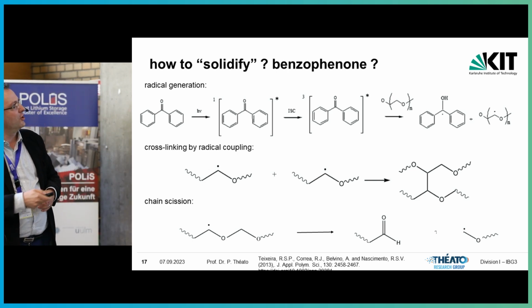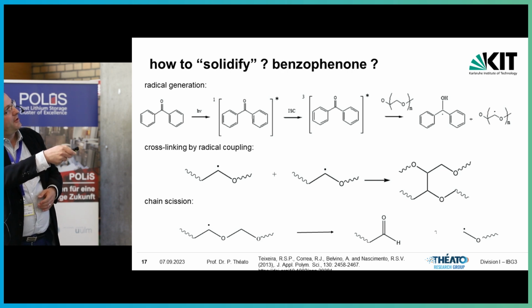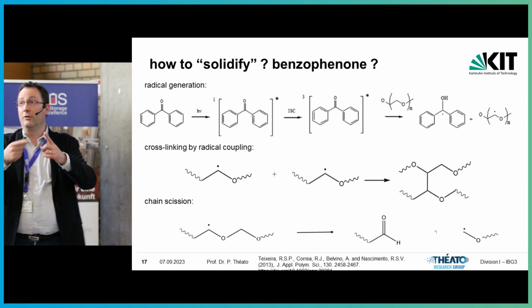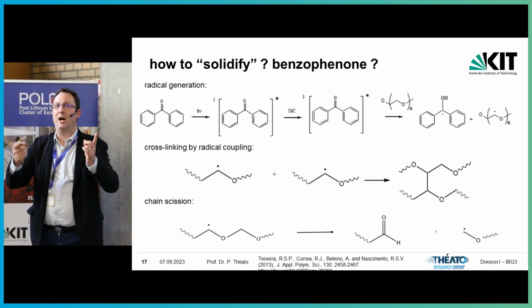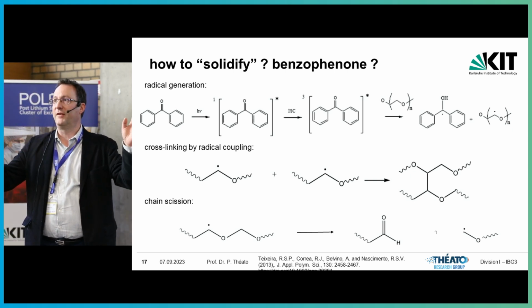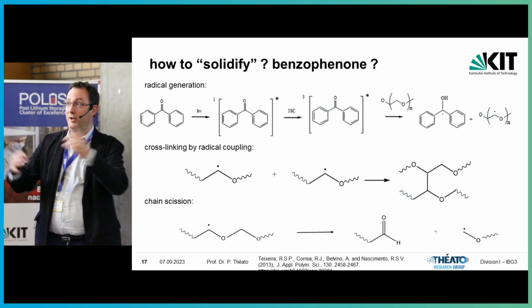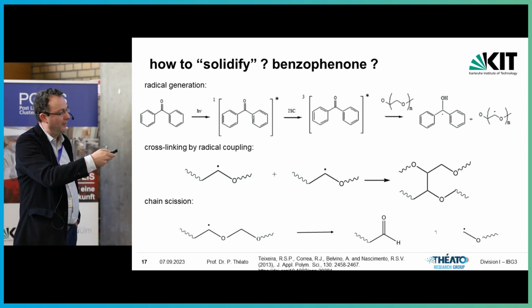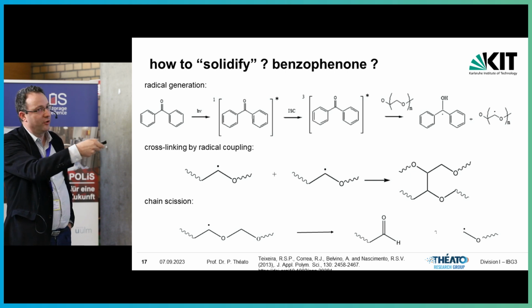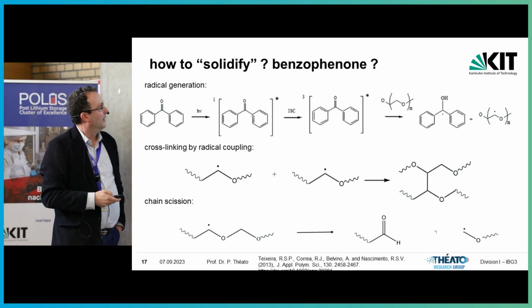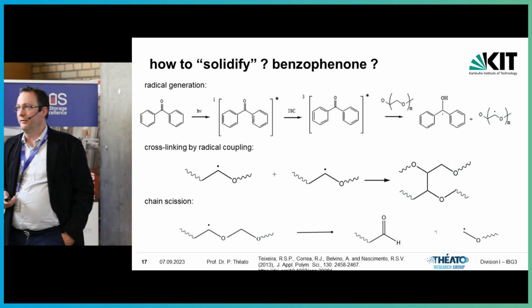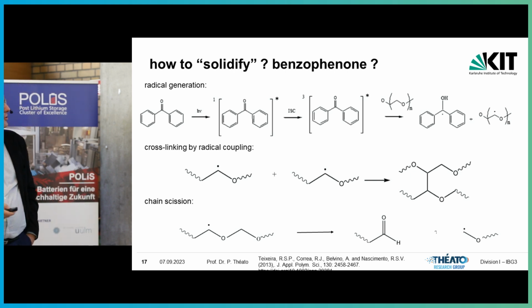But it's not very efficient because the first reaction that is going to take place is that you get the covalent bond between these two radicals. They're the closest neighbors. This is the first carbon-carbon bond you form, and then that's it. You get a CH insertion, but you don't get a cross-linking. Okay, so this is essentially only a side reaction, but it's nice. But the problem is it's not the only side reaction. Okay, there's another one, which is chain scission.